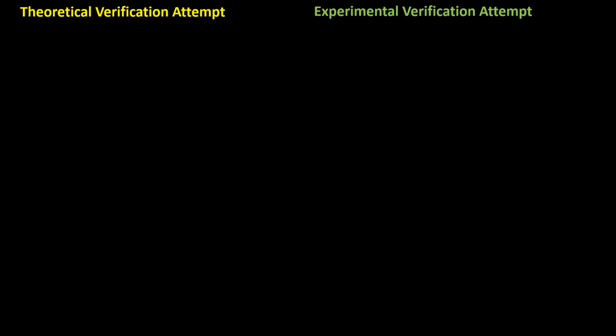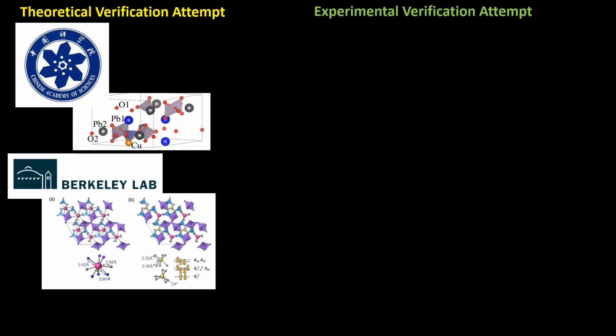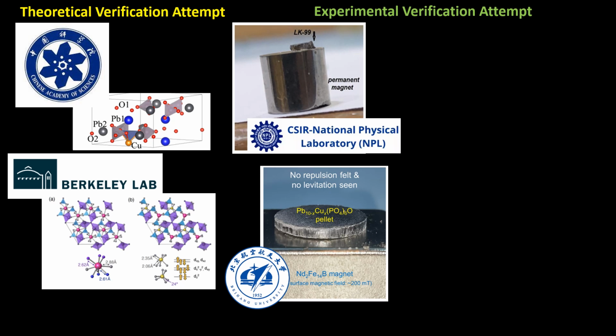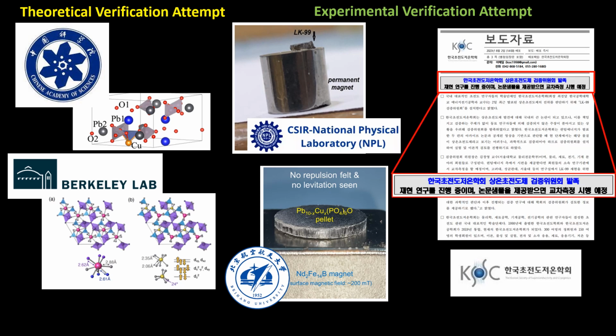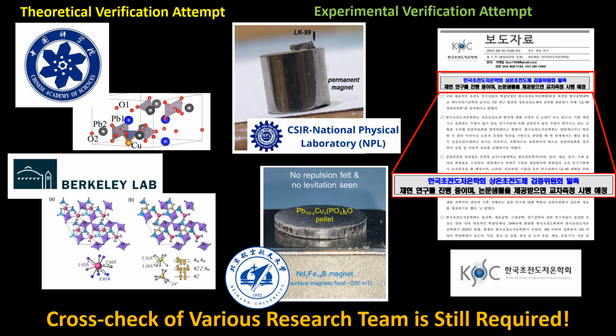Since the announcement of the LK-99 material, numerous institutions have attempted theoretical or experimental verification. Lawrence Berkeley National Laboratory has mentioned the possibility of LK-99 being a superconductor through simulation results. Some research institutes have tried experimental verification such as magnetic levitation and current conduction by creating samples of LK-99. And the Korean Society of Superconductivity and Cryogenics has even established a committee to verify room temperature superconductivity through the confirmation of superconductivity in the sample. However, as of the current results, none of the three main characteristics proving superconductivity have been proven. Cross-verification from various institutions is still needed to get a definitive answer on whether LK-99 is a superconductor.